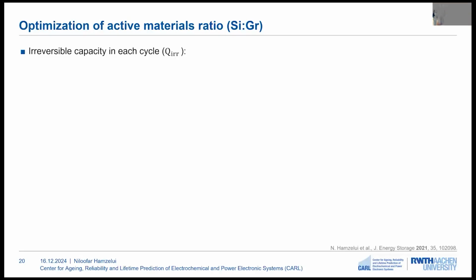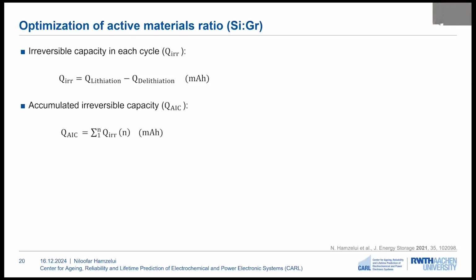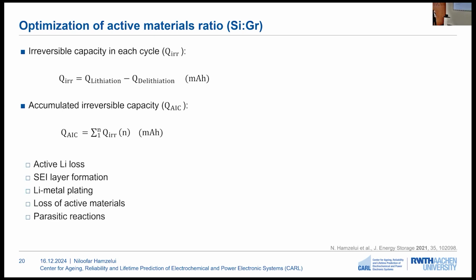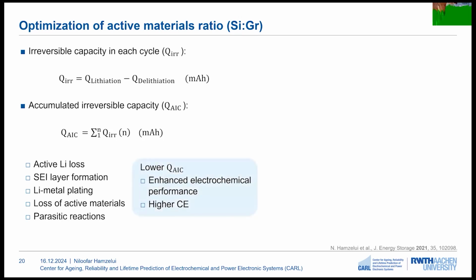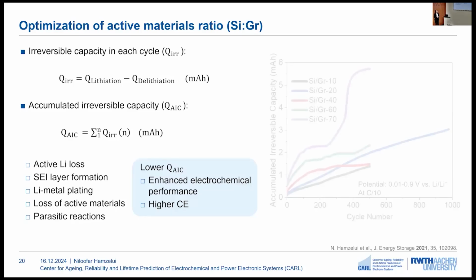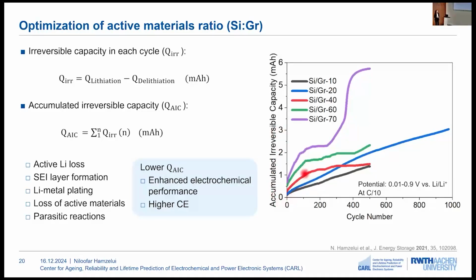The irreversible capacity of the electrodes was also investigated. The irreversible capacity is the difference between lithiation and delithiation capacity. Then the accumulated irreversible capacity was calculated, which is the sum of these irreversible capacities up to a certain number of cycles. This can indicate active lithium loss, SEI layer formation, lithium metal plating, loss of active materials, and the parasitic reactions which are happening in the battery. A lower accumulated irreversible capacity shows a better performance of the cell and a higher Coulombic efficiency. Here we can see the accumulated irreversible capacity versus cycle number for different silicon graphite electrodes with different silicon to graphite ratios.